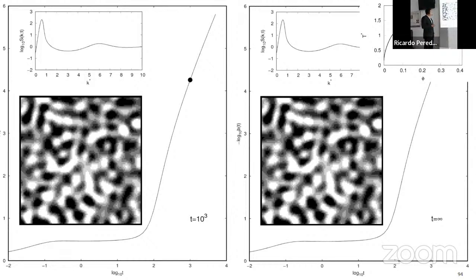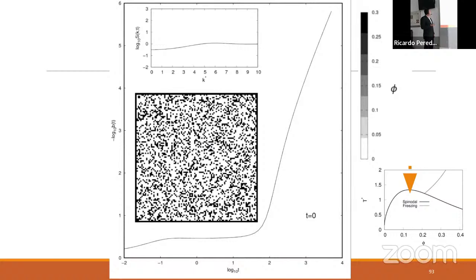And such heterogeneities are, for example, observed along the static structure factor by the appearance of very large peaks at small wave vectors such as this one. Whereas, for example, typical static structure factors from fluid-like systems are such as this one observed, in which no large peak at small wave vectors is observed.